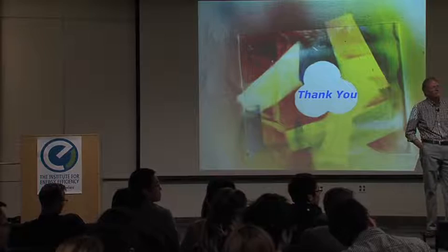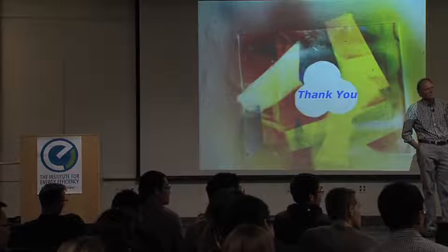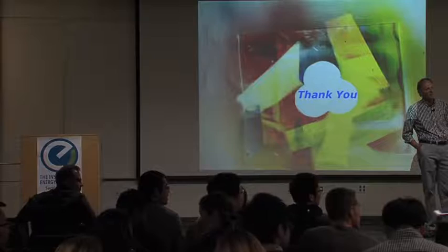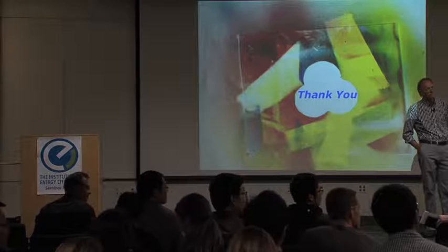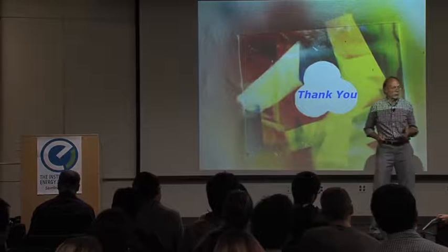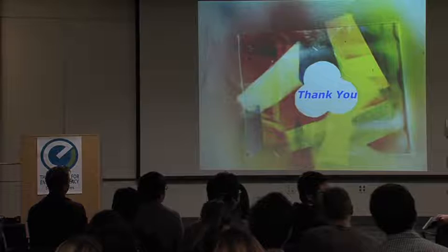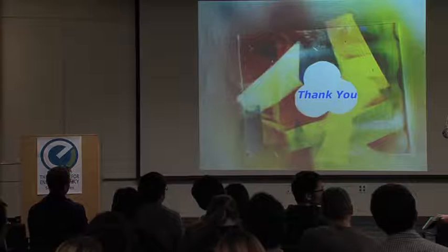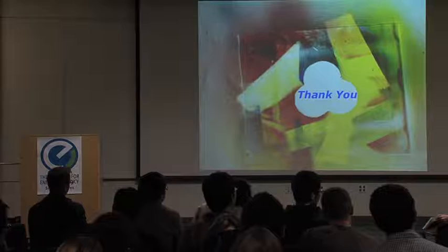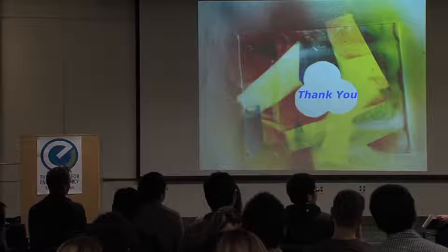Could you comment on the polymer electrolyte you're using between the counter electrode and your electrochromic device, and also... Is that for the electrolyte side or for the whole polymer? I'll answer the first one first. The gram is for the mass of the polymer itself, the whole polymer with the side chains. In fact, one of the reasons for coming up with these cleavable side chains is to get some of that mass out, so that ultimately we would have a higher capacitance, farads per gram, in the ultimate materials. Okay, so that's that question.